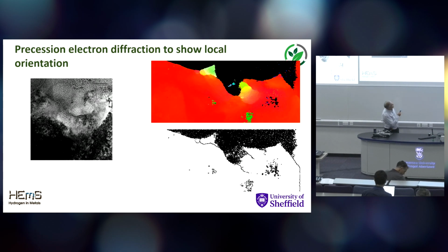This lovely image on the top right is precession electron diffraction, so it's showing you the local orientation, different colors, different orientation. You can see these subgrain areas quite distinct, with abrupt boundaries with the substrate there.